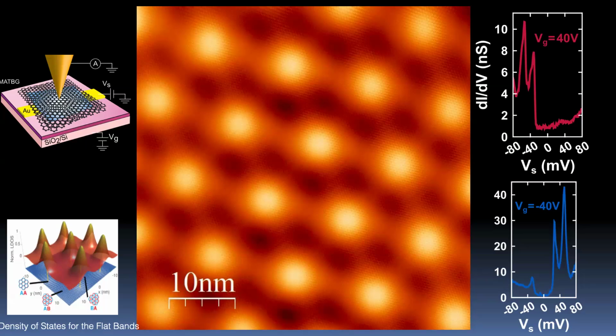Question? Yes. In all of your experiments, you have an exposed top layer, and you have your BN beneath. Is there any reason to think that this asymmetric setup is different to what you get when you have a graphite cap, coated on both sides? Yes, that's right. The electric screening environment is less, so interactions will be stronger in our experiments. Typically in the samples that I show you, our gates are a little further away than in transport colleagues' samples, just the way our samples are made. So essentially we're looking at a situation where the interaction is even stronger. Even stronger, yeah.